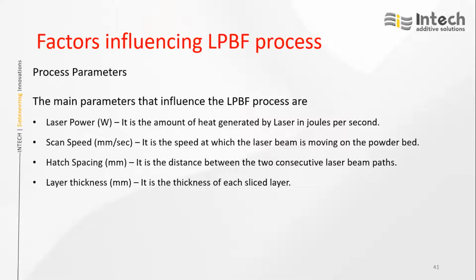What are the important process parameters that need to be optimized? One is laser power, scan speed, hatch spacing, and layer thickness. Laser power is the amount of heat generated by the laser in joules per second. Scan speed is the speed at which we are making the laser beam move on the powder bed. Hatch spacing is the distance between two consecutive laser beam paths in a given layer to cover the entire area. The laser has to go in vector forms. In the video, we have seen vectors. For each vector, the distance between two vectors is nothing but hatch spacing. Layer thickness is the thickness of each layer.